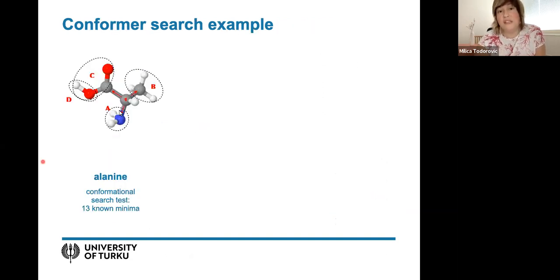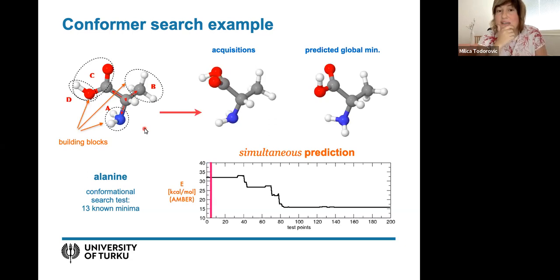Okay, and last computational example is about flexible small molecules, because these are always very important in many technologies. We tested on alanine, which is very small, but it has many different known minima. And we quickly realized that these functional groups typical of amino acids, so the amino group, the methyl group, carboxyl group, won't really change their shape. What will change is the torsional angles between these different groups as the conformation changes. So we fixed these into building blocks, and then we started some active learning.